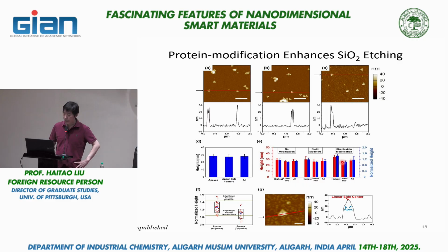So on the edge that has not been modified it is about 25 nanometers. After modification, it's about 35. This one shows a high resolution image of the polymer replication. And again, a deeper trench becomes a higher ridge because it's inversed. Here you see one side is higher than the other two.